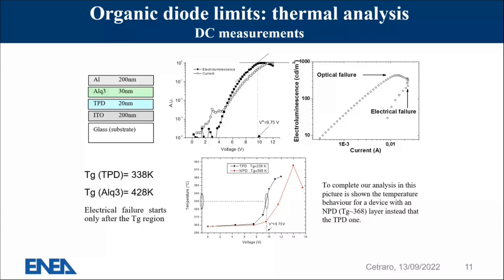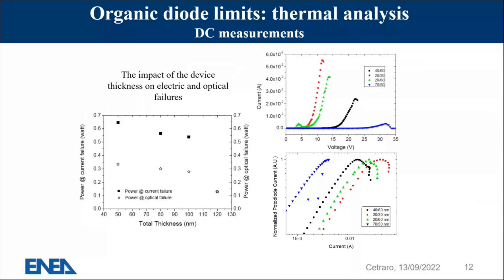You can see that this changes if you also change the thickness of the materials. If the total thickness is lower, you can increase the power, because you can extract the heat from the device more easily. The cathode will also be used to extract the heat. So with a thinner device, you can go to higher power. The optical failure will always happen before the electrical failure with respect to the total power and temperature.